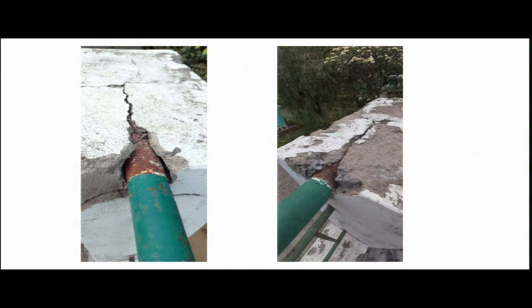And this breaking happens, there are two factors. One is corrosion rust, as is clear from the observation. So, let me analyze this particular failure. What are the observations? The observation is the concrete is severely cracked. And second, wherever cracks happen, huge rust has formed.